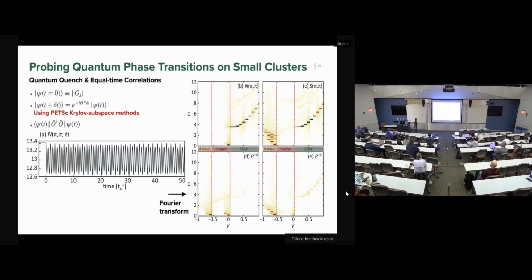Another thing you can do, which I'll skip the details of, is a quantum quench of the material. We know how to evolve our state based on this time evolution operator, which is a matrix exponential. You don't need to compute the full matrix, which is very complicated. If you just do the matrix acting on a vector, we know how to do it with much less effort, again implemented using the PETSc Krylov subspace methods. So you can compute the time evolution and do a Fourier transformation to obtain the spectrum, and you will see that these different phases have different excitation spectra. These are relevant to cold atom experiments. You can actually measure them directly in experiments.